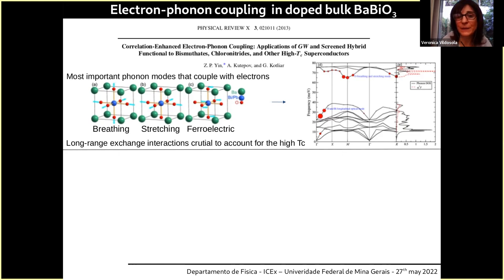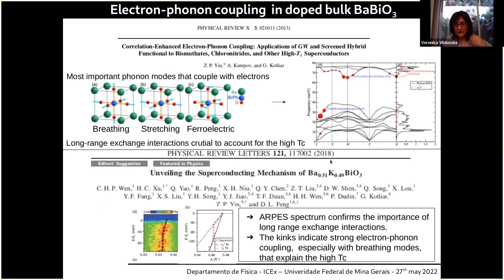So with this paper, they solved a problem in the literature. There was no consensus on what was the origin of the superconductivity in this material, and they demonstrate that it is electron-phonon coupling. And then 3 years ago, they could measure the electron-phonon coupling through ARPES, angular resolved photoemission spectra, and they observe kinks that indicate strong electron-phonon coupling, especially with breathing modes.